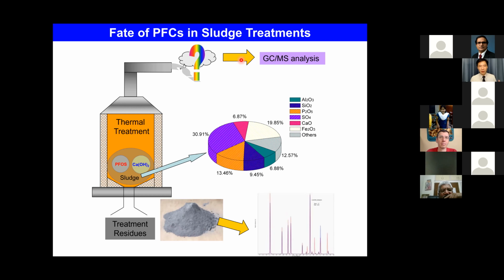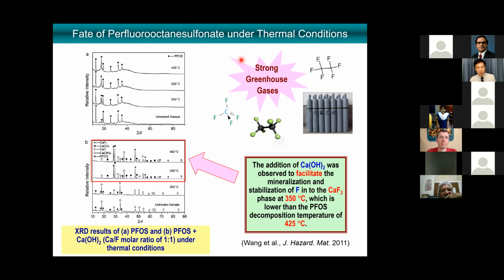Okay, this is what we find, and this was really, really interesting for us when we first started dealing with this. I think we're kind of the first in the world dealing with this kind of reaction with the PFC. We were very excited. It was actually a little bit more just try it, see what happened. We find out at 350 degrees Celsius that fluorine can actually react with calcium and form a very famous mineral called calcium fluoride. And again, this happened at 350 degrees Celsius, which was lower than a temperature of 425.